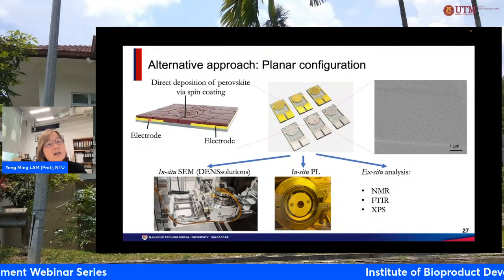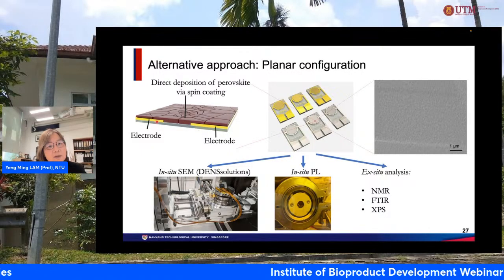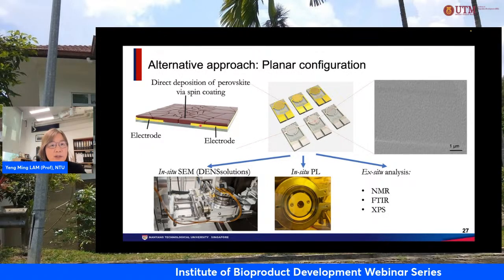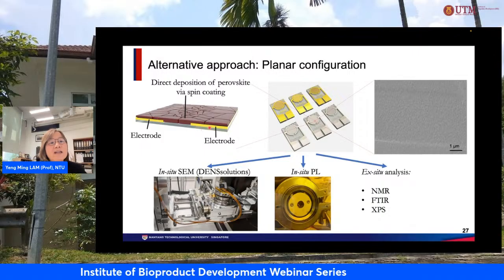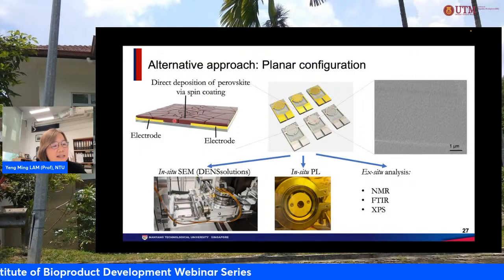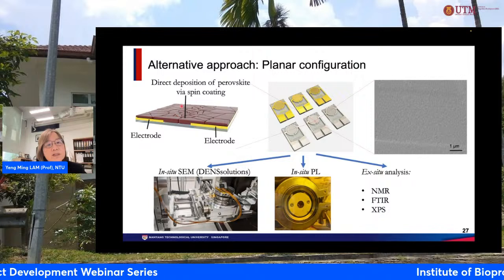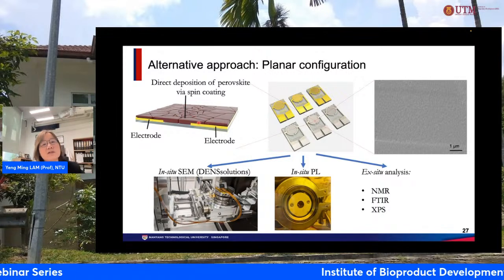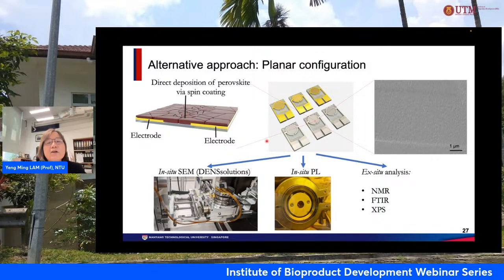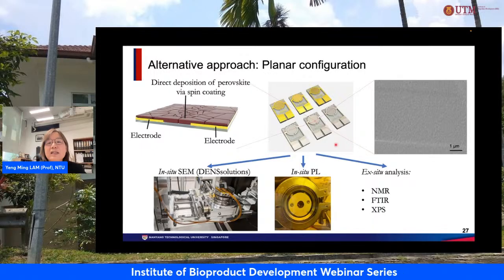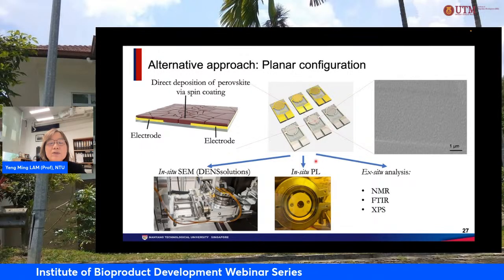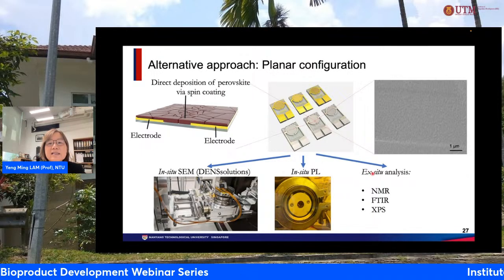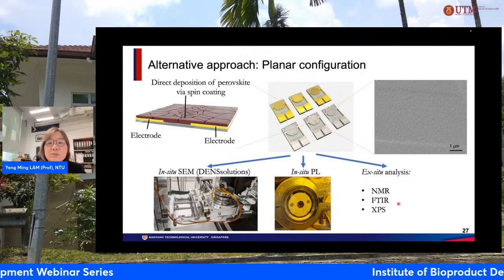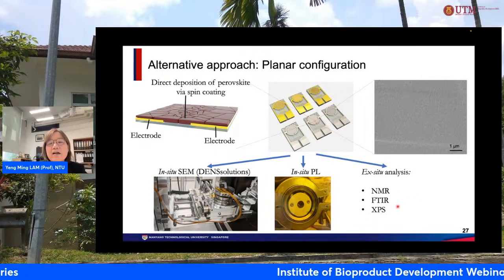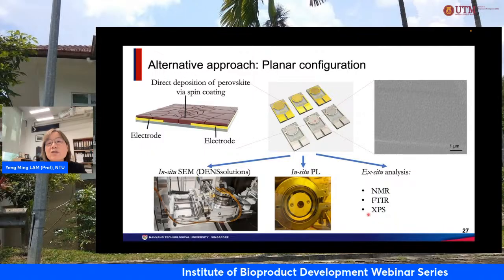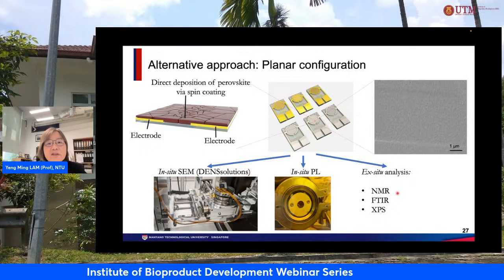So we have now changed the way that we prepare this material. We use patterning, the same as a microelectronic platform, where we pattern the electrode, and then we deposit the material on top. This is the perovskite. We just spin coat it on top, and then with this material, we can now look at it under SEM, look at it under TEM. We can also do in situ photoluminescence and ex situ chemical measurements. So all these NMR, FTIR, and X-ray photoelectron spectroscopy studies we will conduct on these materials.